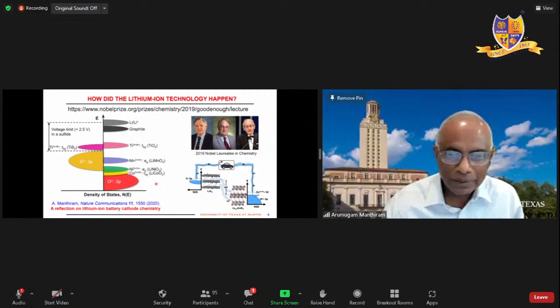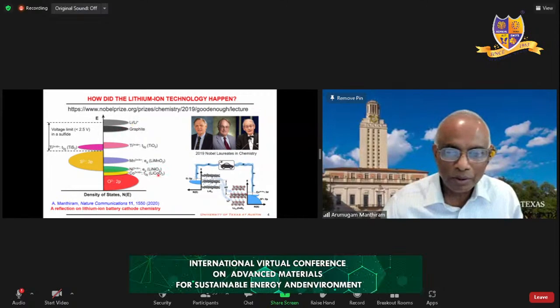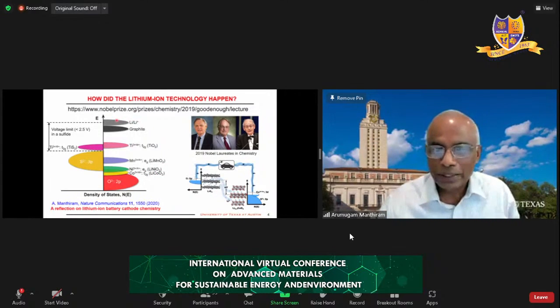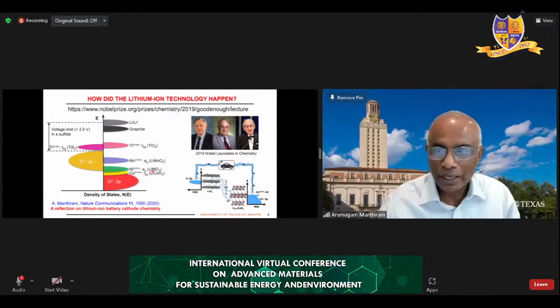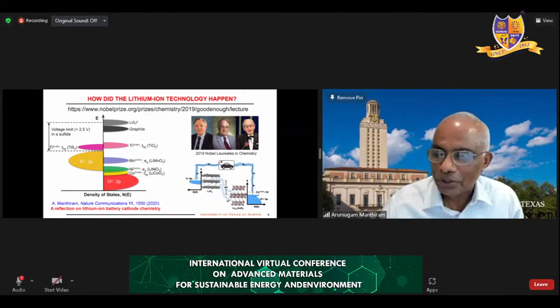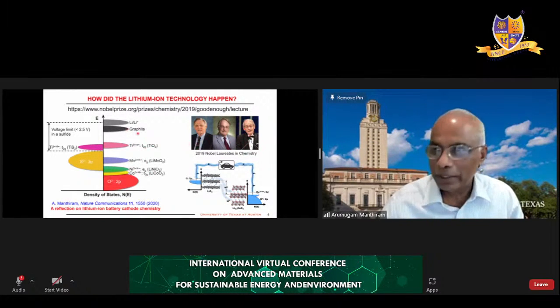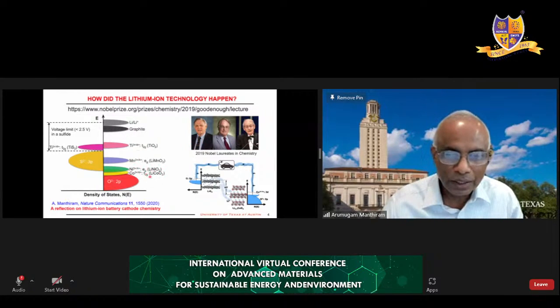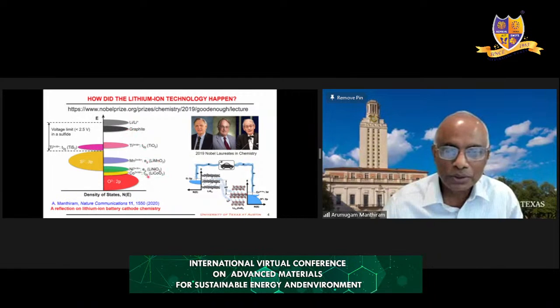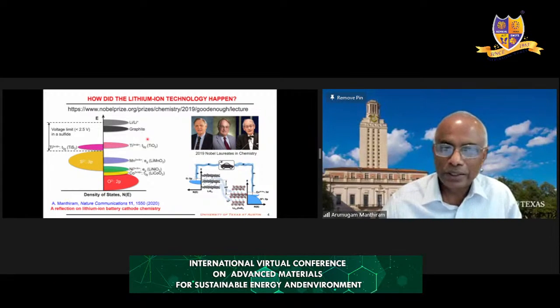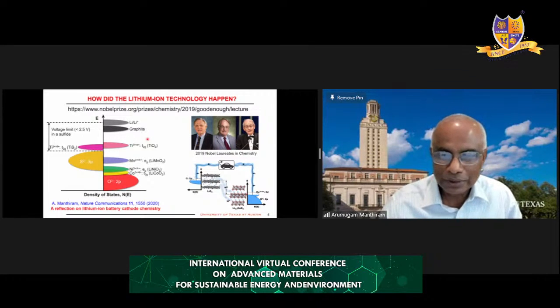Don't worry, I will have lithium in my cathode. So I will choose my cathode like lithium cobalt oxide, lithium already there. I will first charge and put the lithium ion into here like I was showing in the other diagram. Very simple, that made it. Then Yoshino Akira in Japan was working on carbon-based materials as anode. As soon as he saw lithium cobalt oxide, he coupled the carbon anode and lithium cobalt oxide, carbon as a host, and then he demonstrated the very first lithium ion technology. And then Sony used that patent and they announced commercialization in 1991, and that's what we have here. And since 1991, same chemistry, but the only thing changing is engineering.